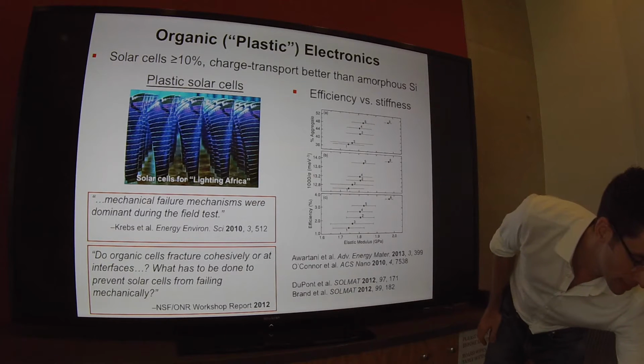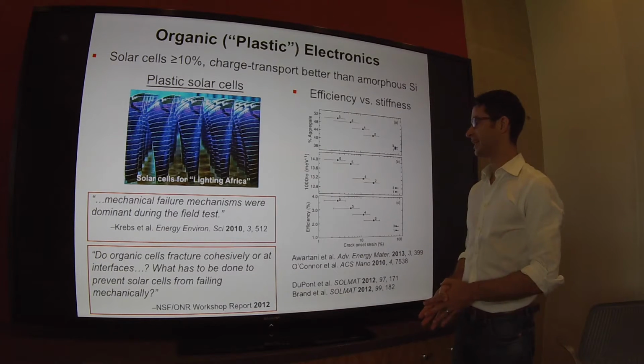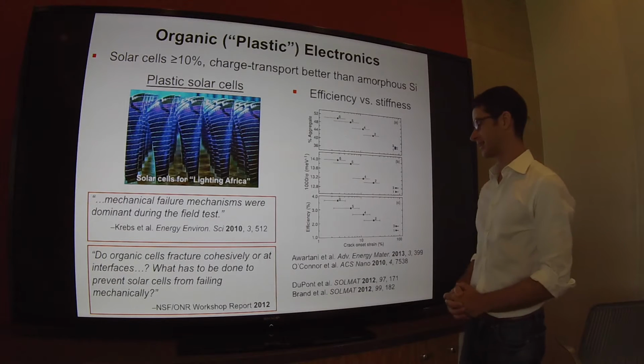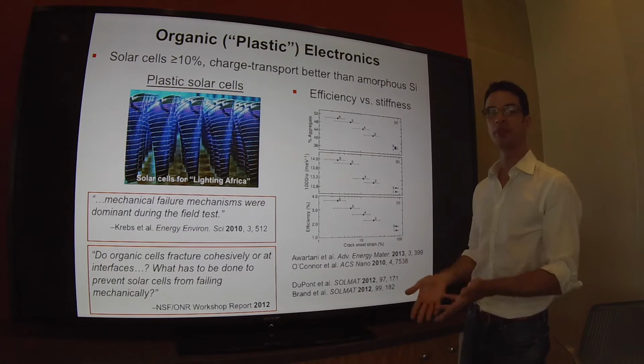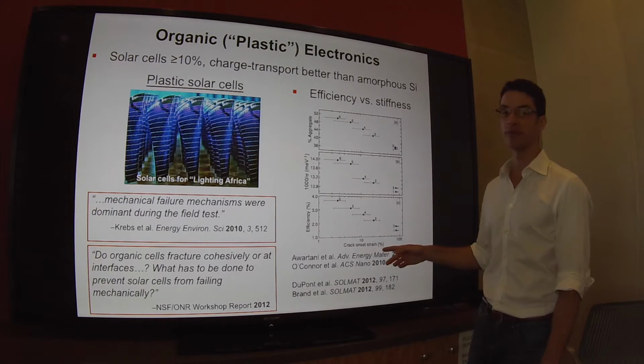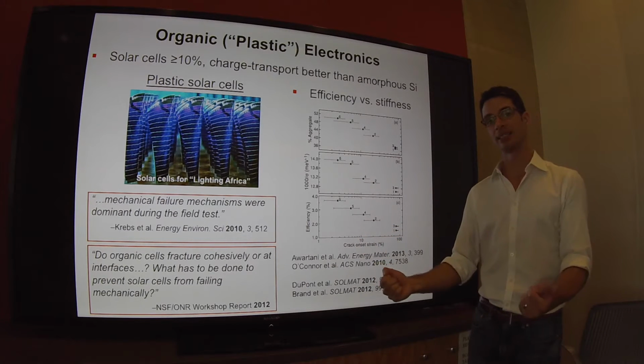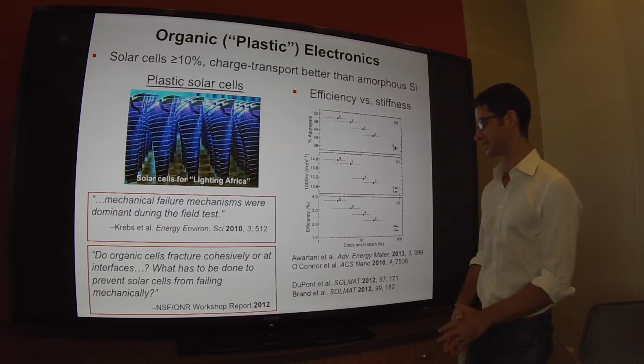So the researchers also published an analogous study of the brittleness. So as the efficiency goes up, the order goes up, and the brittleness in the form of the crack onset strain on an elastic substrate also increases.